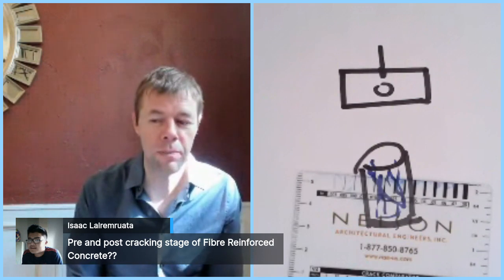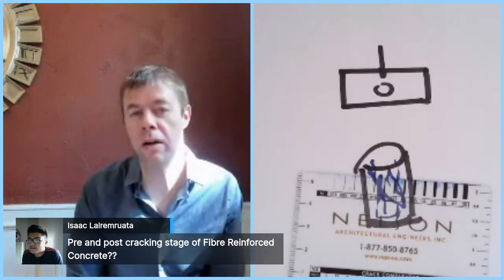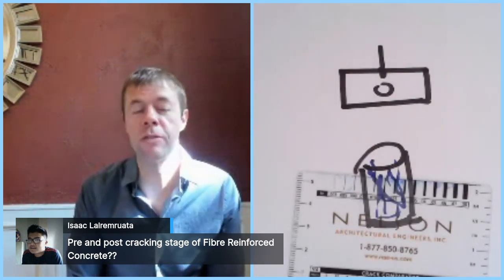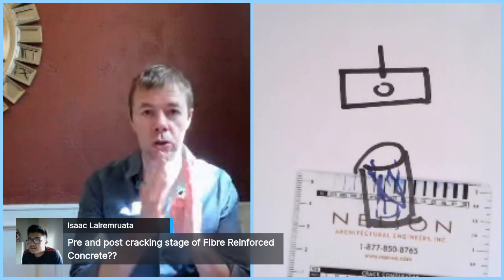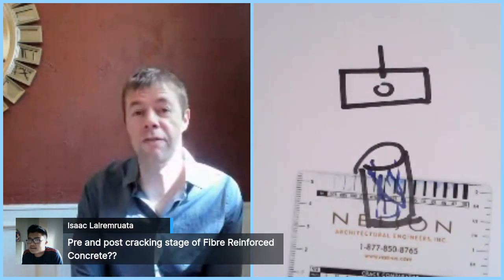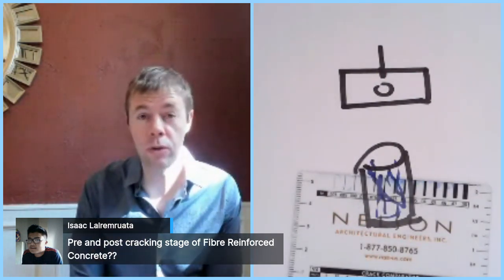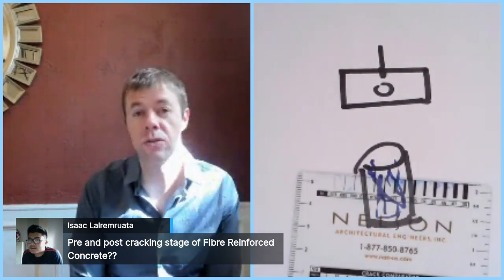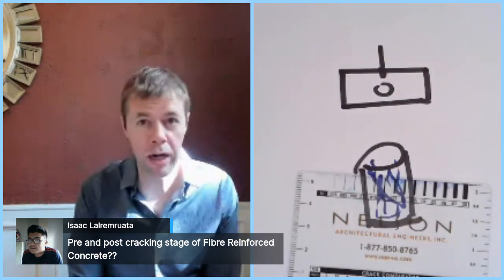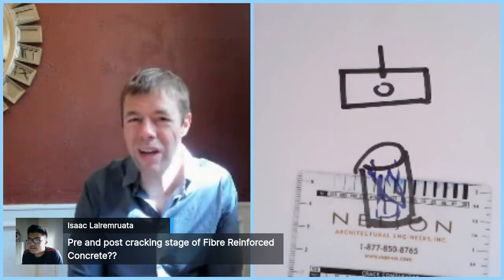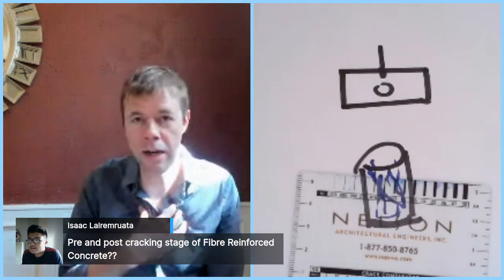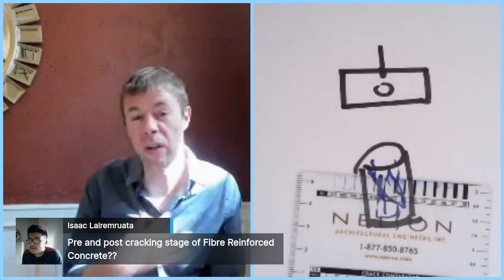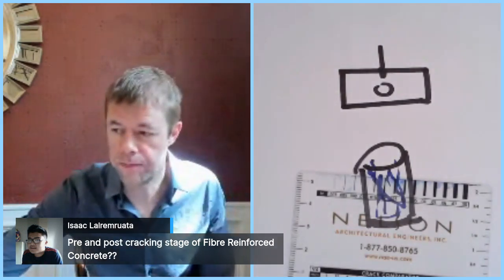And then post-crack. It depends what you mean by post-crack. How big of a crack? You mean like end of life type stuff? There's a lot of data out there and a lot of work that's been done on post-crack, as in really large cracks that happen inside fiber reinforced concrete. And fiber reinforced concrete works great in both these applications. We've got really good data on these early age cracks, and a lot of data already exists on the larger size cracks. Now, when the cracks get really large, in my opinion, I don't think fibers help as much. I think they're much more valuable when the cracks are very, very small. At least that's my interpretation of your question.